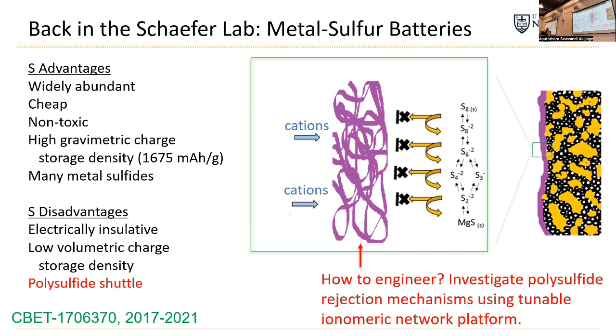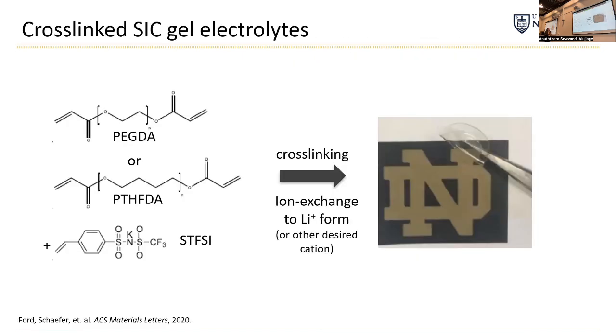And so he was making ionomer networks by taking very simple macromonomers here. So this is PEG, for example, with acrylate groups. These are polymerizable groups on each end, so it's a difunctional molecule. These are very cheap, and you can buy them commercially at large scale. And he was polymerizing this one with this ionic monomer, which wasn't available commercially at the time, but now it is, you can buy it. And he was making these cross-linked gels to look at some fundamental polysulfide screening things.